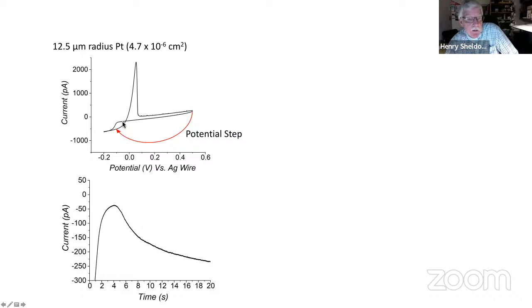And you can step to different potentials, and the curves change because as you go to more and more negative potentials, the overpotential or the driving force for nucleation is increasing. And so the response here is a function of where you step, okay?